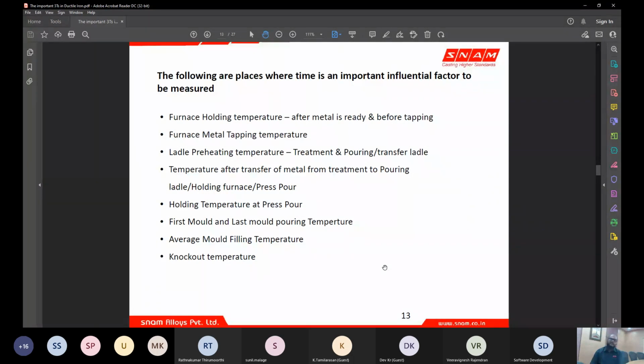And ladle preheating temperature. We are being advised by foundrymen and experts to maintain a very high ladle temperature, so that you reduce your tapping temperature and the temperature loss during treatment and during transfer is taken care of. But there is a catch.